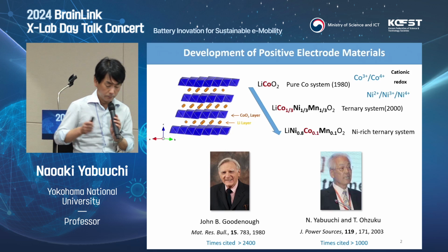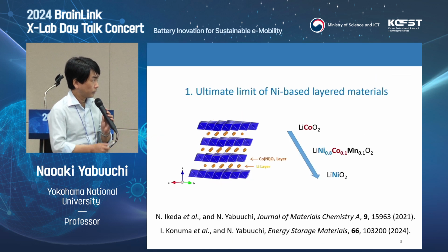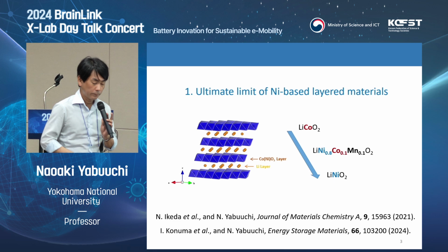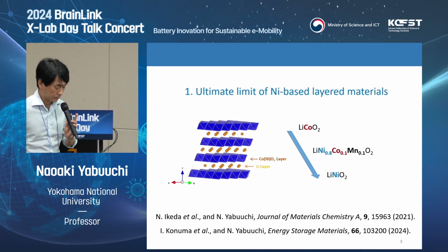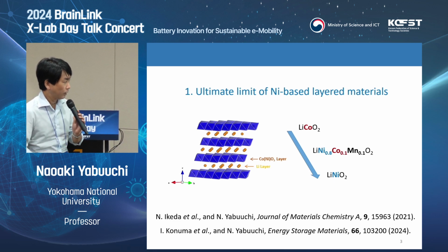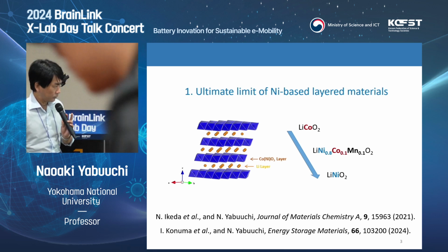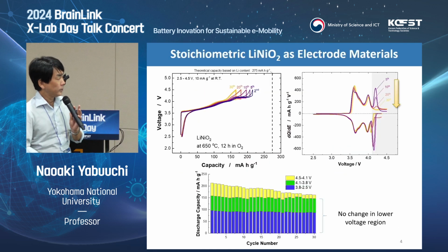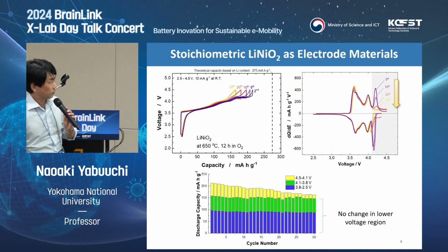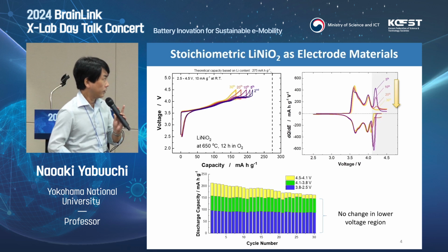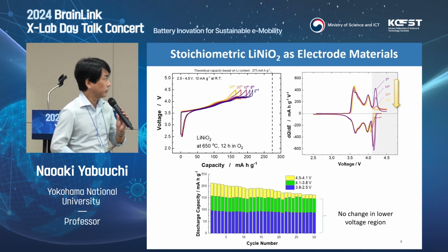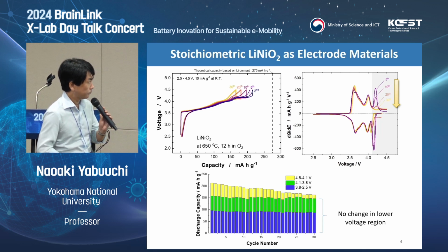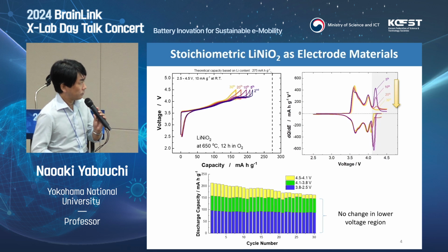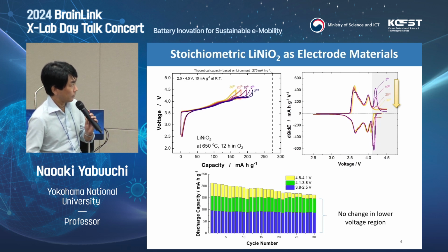Then my first topic today is, can we make a pure nickel system without cobalt ions, a cobalt-free pure lithium nickel oxide? This is our publication about this topic. First, let me show you stoichiometric lithium nickel oxide. This sample is very difficult to manage, and degradation is always observed upon cycling. Here you can see typical charge and discharge curves for 20 continuous cycles.